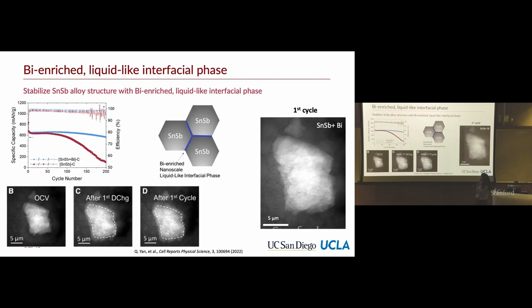And so what we think is these bismuth-enriched grain boundaries are allowing the grains, as they expand, to slide past each other. It's kind of like steel, where you get a lot of structural integrity because of the grain boundaries and the architecture of the grain boundaries. And so we think it's like a liquid-like interface between the different grains of the structure. Each of those grains are expanding as you lithiate and pushing against each other, but they're allowed to slip past each other rather than cracking.